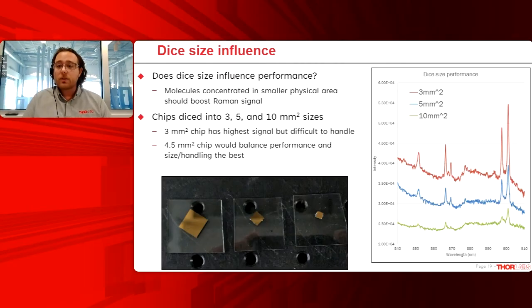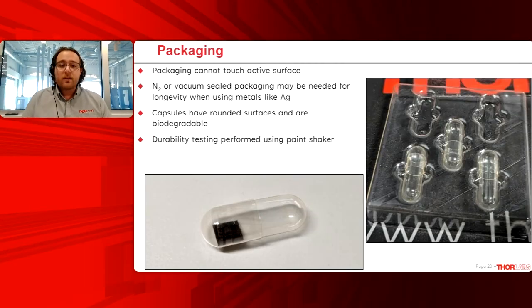Now, another thing we have to characterize is, now that we've diced these substrates, how do we get them to customers in a good condition? And this is where we have to characterize our packaging solution. So in this case, we have all of these nanostructures on the surface, and they can very easily be damaged. So the packaging can't actually come in contact with the surface at all. So what we found is gelatin pill capsules were a really nice solution to this problem.